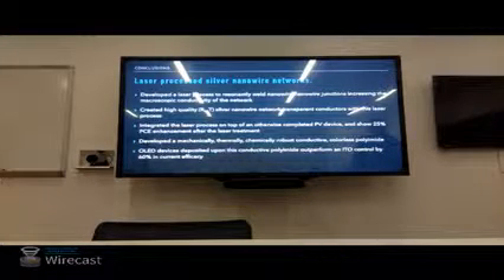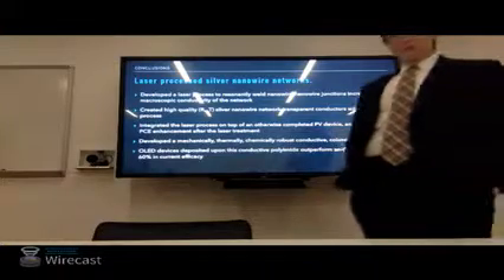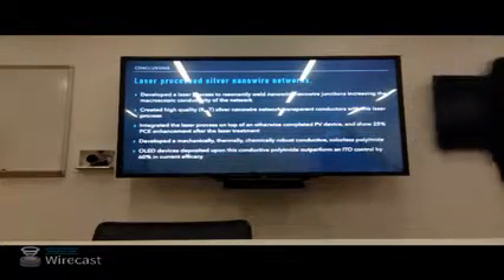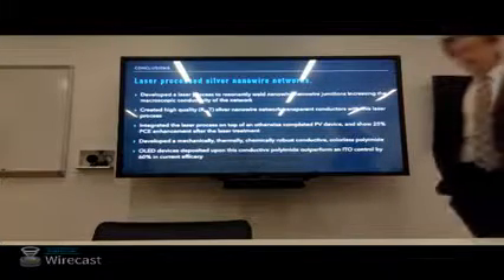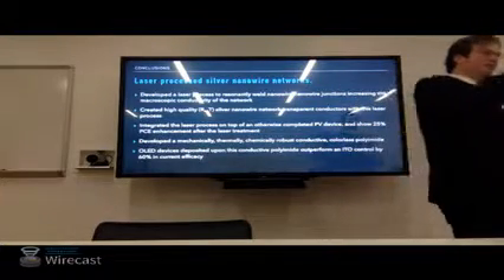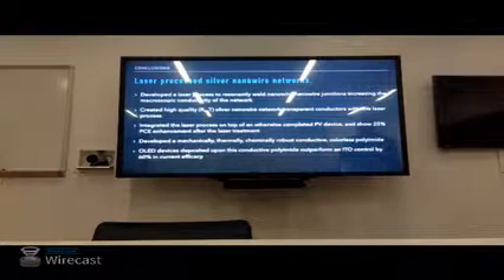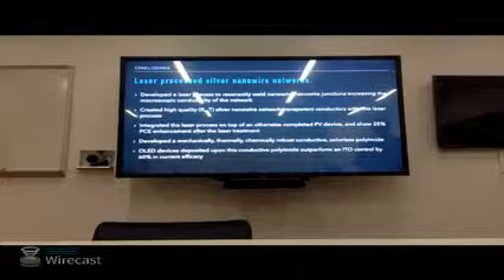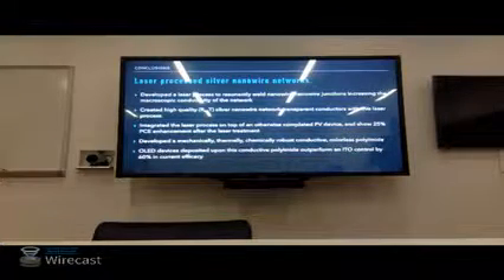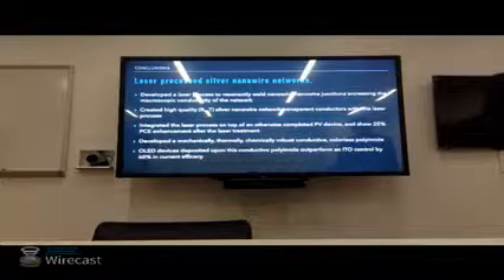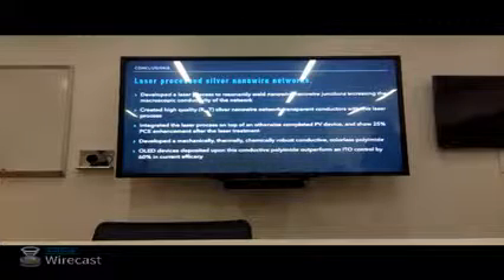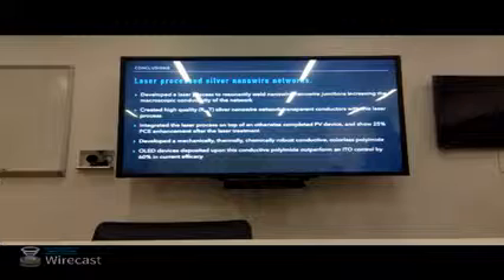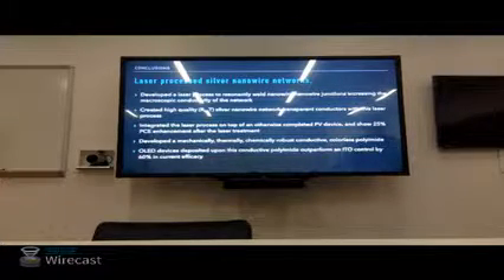In the solar cell work, because the silver nanowires are our last layer to the outside world, I don't have to worry about any sort of mechanical role of that interface. The OLED work is a totally different beast. As I mentioned, we need to use polymer encapsulant for the surface roughness. That polymer, with the nanowires in it, has to be robust enough to stand up to deposition and then do our mechanical testing. So we get for free all the beautiful things that come with a polyimide. However, we've tried things like polystyrene, which has a reasonable index of refraction. It's just too brittle, or it doesn't play nicely to encapsulate all the roughness of the nanowires. So the interfacial mechanics really comes in when we need to peel it off from our glass, right? We need to know which side the nanowires are going to stay on.